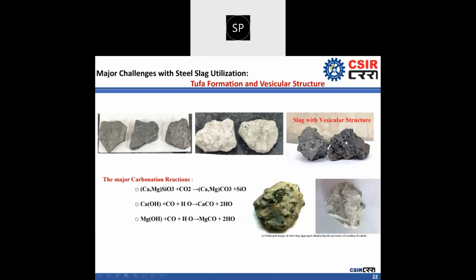The third challenge is slag with vesicular structure. If the slag cooling process is not properly customized or scientifically handled, then the slag generated after cooling will be of this type, with this surface appearance, and by virtue of this vesicularity, this slag will have higher binder demand, in terms of bitumen binder or cement. Since the binder will pour into all these voids and then cover the surface, the binder demand will increase significantly. So this vesicular structure can be controlled by adopting a controlled slag cooling process. So these are the two important aspects.